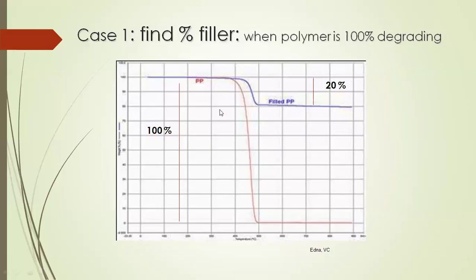So what you can do, if in your quality control one of your products fails from the same manufacturer, or if you change the vendor and your product is failing, first do a simple TGA of your quality control passed and failed samples. How to find out the filler percentage in the polymer? This is the case when your polymer is 100% decomposing, meaning there is no residue.